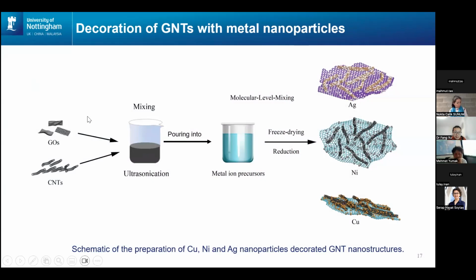The first step is still the same. So we mix graphene oxide and carbon nanotube using an ultrasonic probe. In the meanwhile, we prepare metal ion precursors, so it could be many different metal salts, okay? We're going to talk about them one by one. Examples here like silver, nickel, copper. So we have silver acetate in this case, nickel acetate, copper acetate.